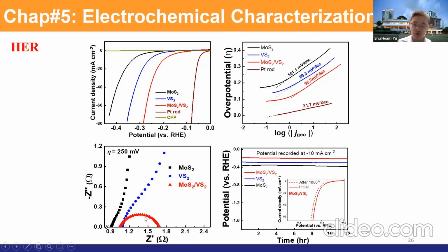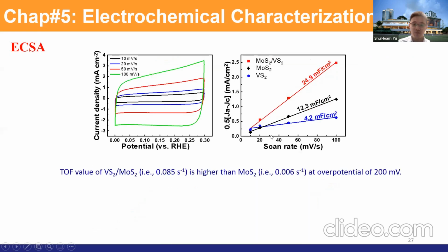And then we also perform the Nyquist plot. So this is the MoS2 and VS2 electrode. You can see it forms a semicircle. If you increase the potential larger, this one can also form a circle, but the semicircle will be large, with a diameter significantly larger than MoS2 and VS2. And then we also perform a stability test. You can see that there is negligible potential change over 12 hours. And we measure the surface area, and we find that the surface area of our electrode material indeed increases. And also the turnover frequency of our hybrid sample is higher than the standalone sample.